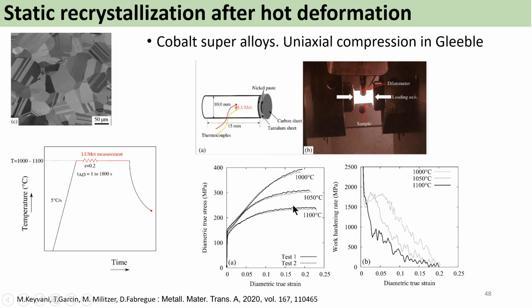showing no sign of reduced flow stress. That is to say, we have no occurrence of recrystallization occurring during the deformation. So all the recrystallization will occur after the deformation.